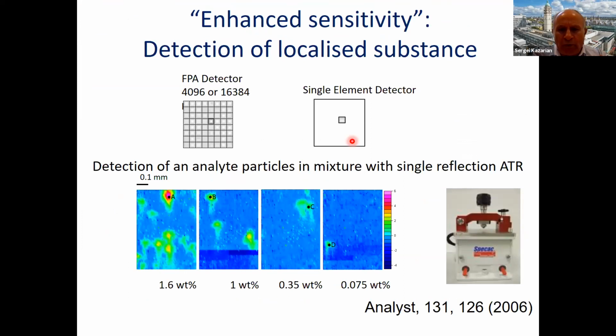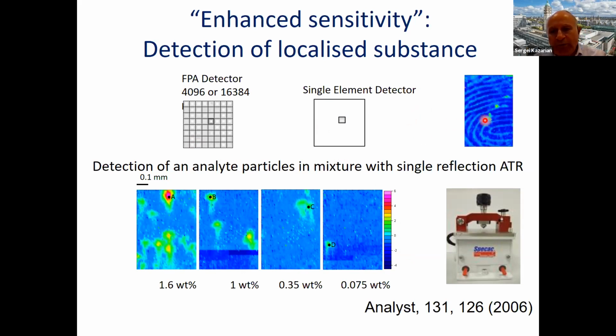So one more point about chemical imaging with array detectors, with infrared array detectors. If you use a single element detector on an infrared spectrometer, your information would be average. And if some particle is present here, it would usually be overwhelmed by spectral information from all the sample. So it's average. With an array detector the situation is different, and I have done such experiments here, diluting powder of 2 different components further and further. And you can see we can detect almost pure spectrum, because from these locations we can obtain pure spectrum of this particle. And we use it in forensics very much. For example, here particles are trapped. With a single element detector, it would not be possible at all.